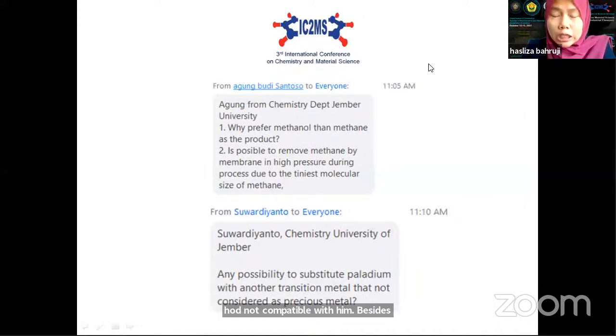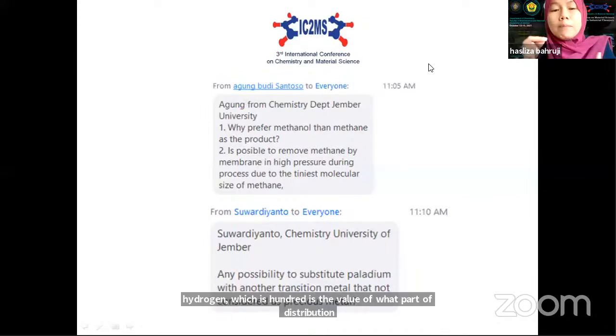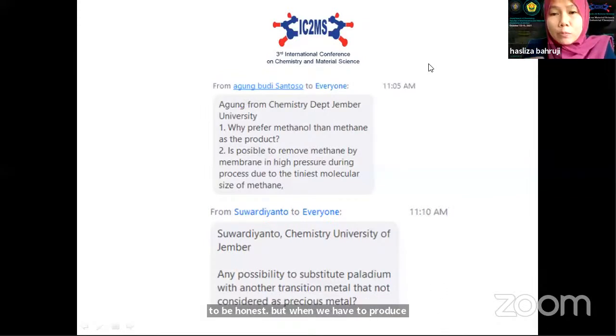Besides, when you look at the equilibrium reaction, the stoichiometry of reaction for formation of methane actually requires 4 moles of hydrogen, which is the valuable part of this reaction, to be honest. But when we produce methanol, it only requires 3 moles of hydrogen, so we reduce the amount of hydrogen that we require to reduce the carbon dioxide.